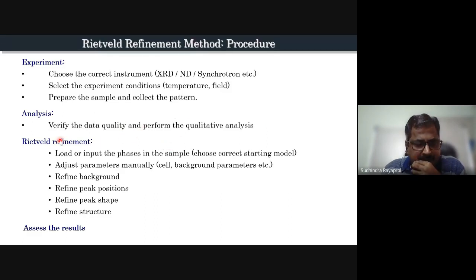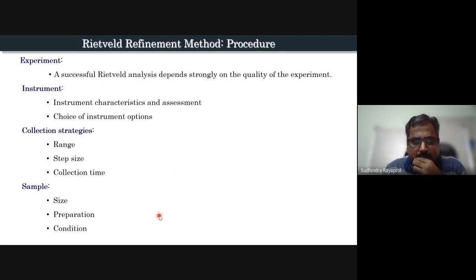For Rietveld refinement, you have to choose the correct starting model, a proper model which is isotypic or isostructural to your sample. You have to adjust parameters like cell and background parameters. You define the background, the scale, the peak position, the peak shape, and the structure. The order is that you start with the scale parameter, cell parameters, background, positions, shape values, and the entire structure. Then you can assess your results and see how it looks. Successful Rietveld analysis depends strongly on the quality of the data, the quality of your experiment. It depends upon the instrument characteristics and the choice of the instrument options.